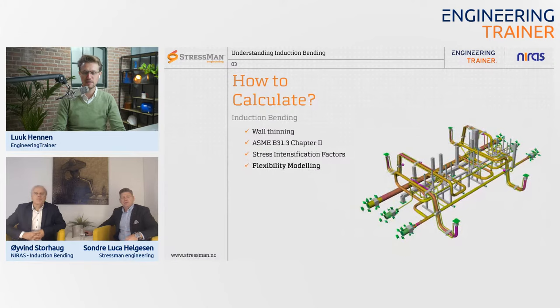All right. And then this is just an example from a subsea manifold that we did a few years back. As you can see, there are a lot of bends in there. Every single bend in this model is an induction bend. And these are 6-inch pipes, schedule XXS or extra extra strong. The 2-inch is schedule 160, same as the 3-inch is schedule 160. So quite significant wall thickness on these ones.